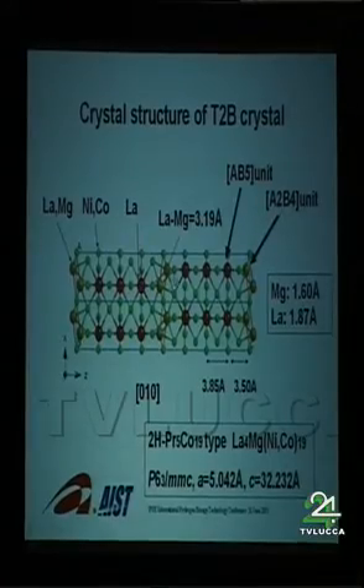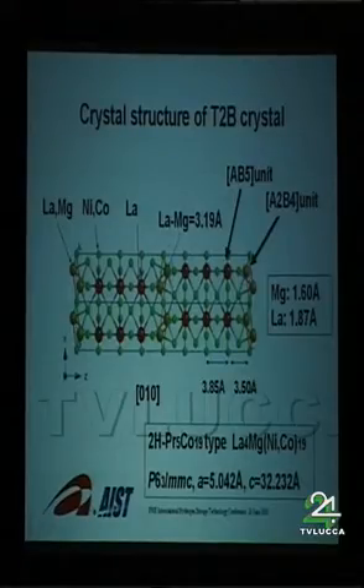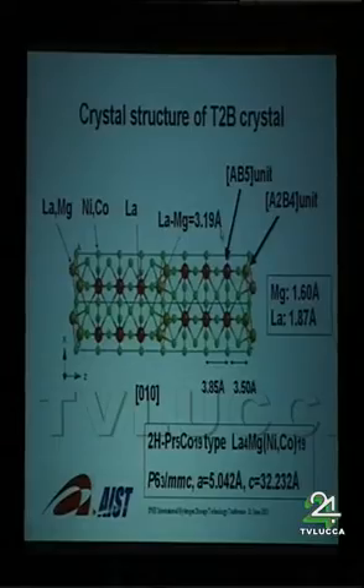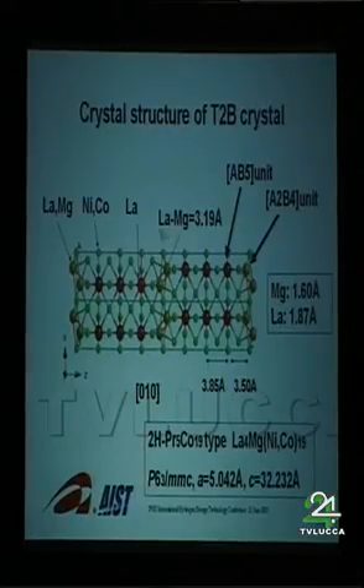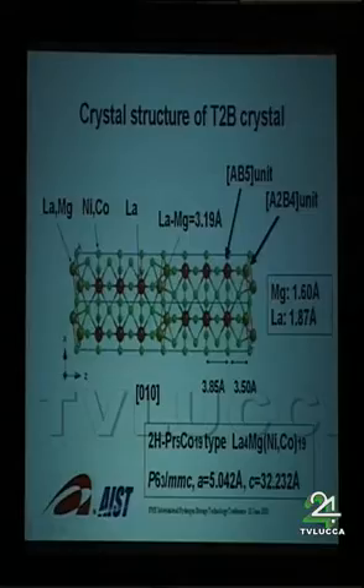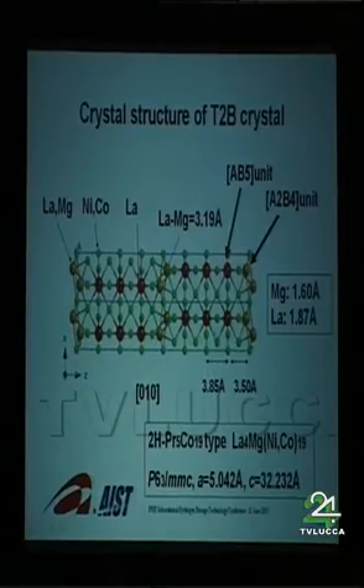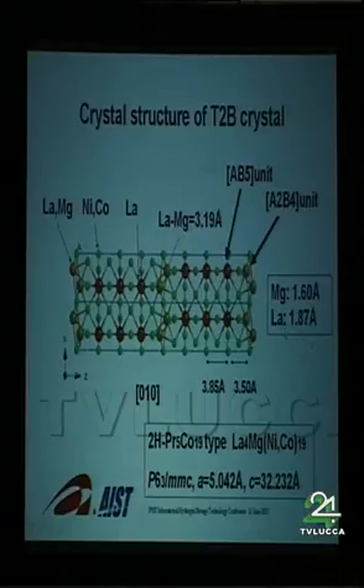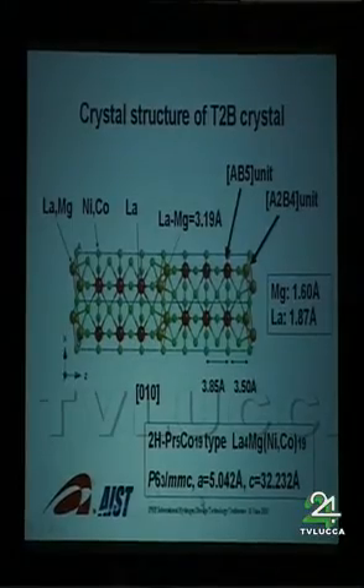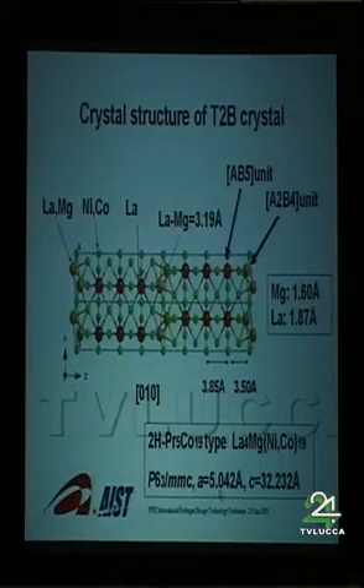The reason is very simple. The lanthanum-magnesium distance in this unit is 3.19 angstrom. If we compare the atomic radii of magnesium and lanthanum, only magnesium can occupy this site. But in the other AB5 type unit, only lanthanum occupies those sites. We can easily distinguish this bond direction, 3.85 angstrom, between two AB5 units, which is just double of this value. And this structure can be described by this space group, and the lattice parameter is just 5.04 angstrom in the A axis, but the C axis is 32 angstrom.